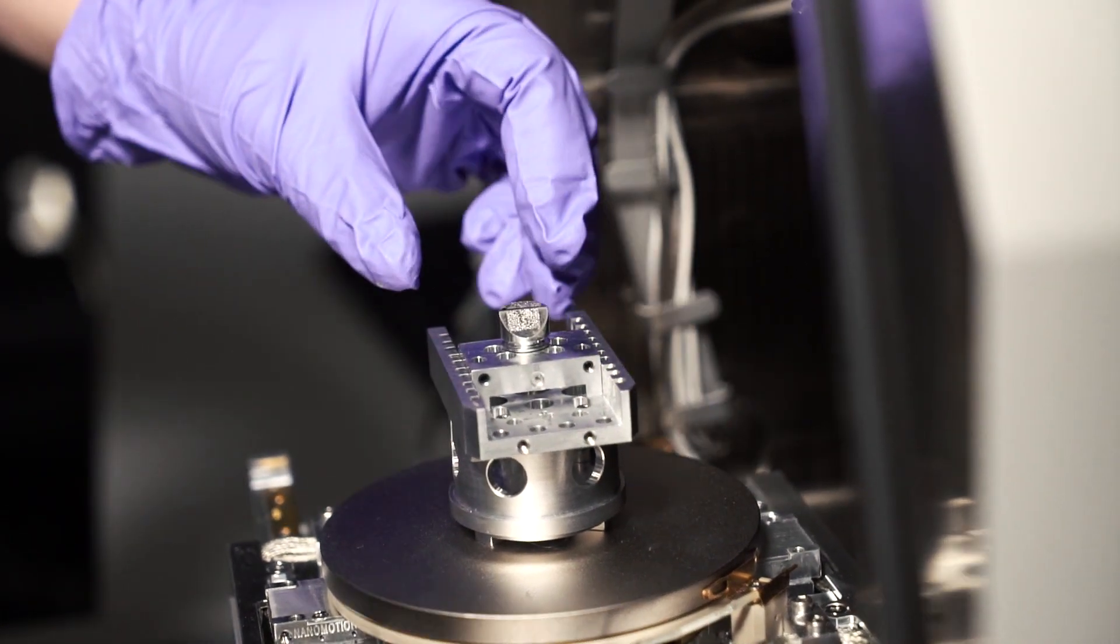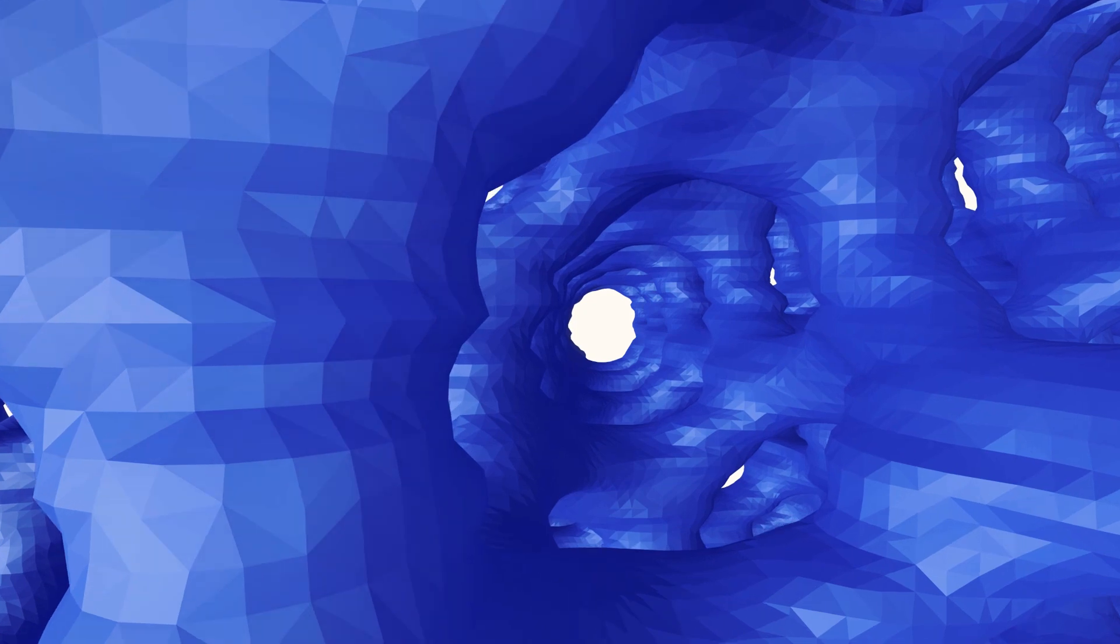It turns out the structure is distorted. The real structure is not in the pure mathematics but in the real materials distortions occur. And we were able to measure those distortions quite accurately using this slice and view technique.